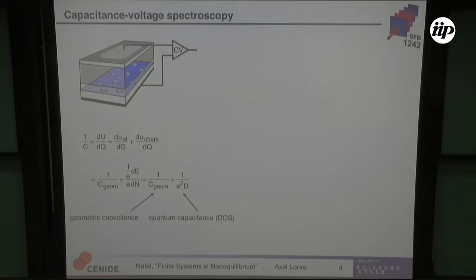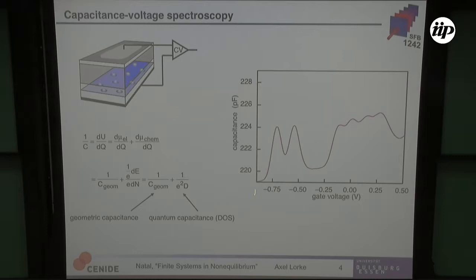and so it works wonderfully. And when we plot the capacitance as a function of the gate voltage, we see these wonderful peaks. And when I show you plots like this, think of it as an energy scale. All you have to do is divide this by e, and then you have the energy in electron volts. And think of this in terms of the density of states. And you see that in this layer, you have a density of states at different energies, and you see a spectroscopic fingerprint.